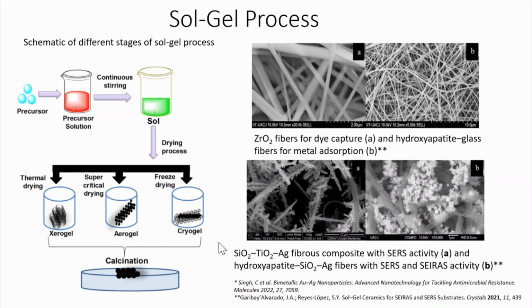The production of ceramic nanofibers, here you can see it, with high porosity makes the surface area even greater, with successful results in most cases of application. Avila Martinez and colleagues produced a zirconium oxide material obtained from the sol-gel method using zirconium butoxide as a precursor mixed with polyvinylpyrrolidone and electrospun into fibers for the capture of allura red dye. Average fiber diameters range from approximately 100 nanometers to 300 nanometers. Here you can see some examples of different fibers.